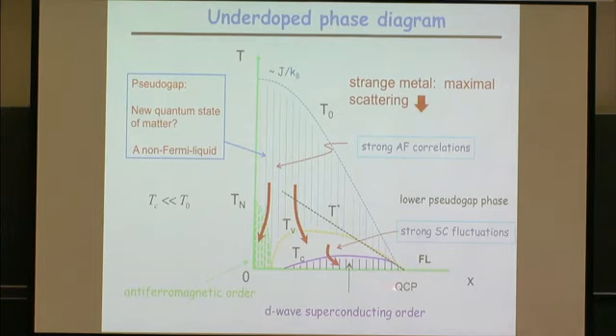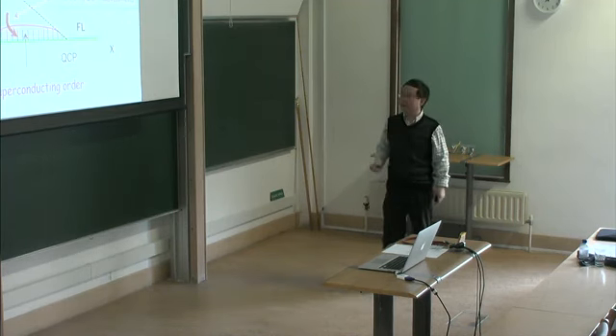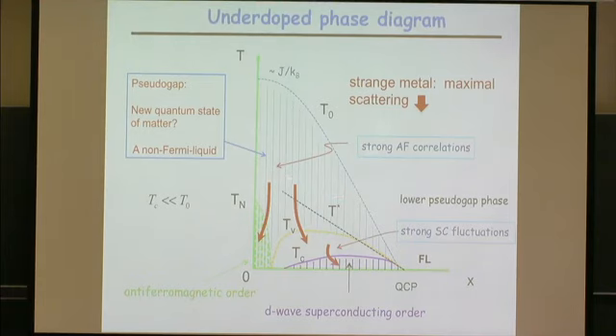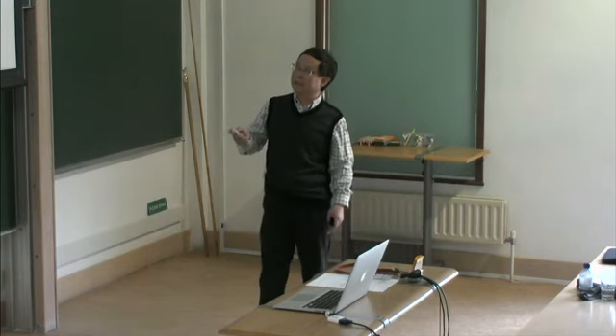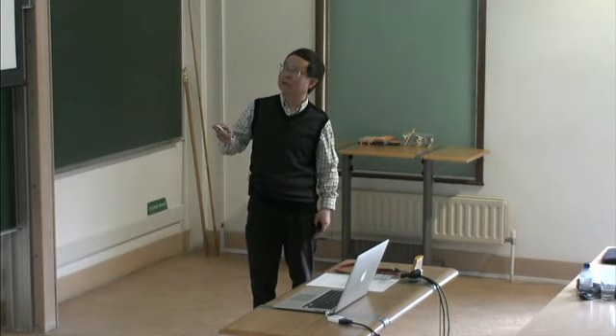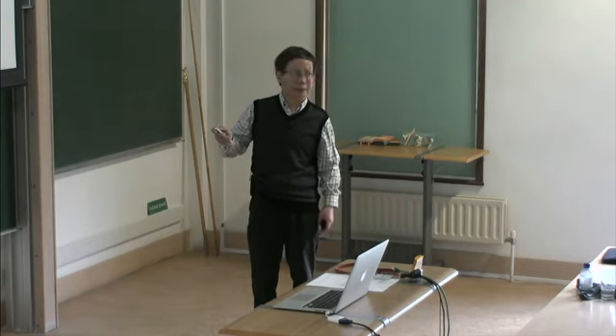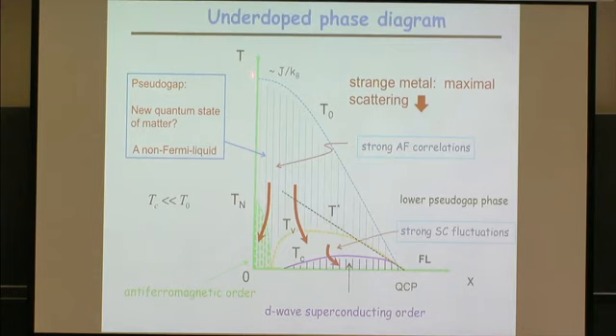high Tc superconducting state. But the interesting thing is that there's a huge range in the phase diagram where you don't necessarily have a true long-range order, but you see a lot of fluctuations. Actually, you can detect the antiferromagnetic fluctuation at the order of J temperature. That's 1,000 Kelvin, and with decreasing temperature at half filling or near half filling, you go to a long-range ordered state.